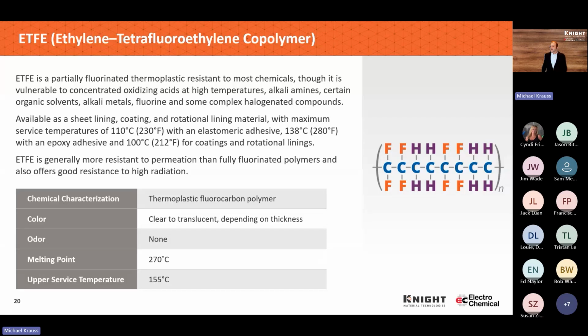There are challenges in getting a thick film spray coating, but this is a material that has been used and does extremely well for rotational linings. So it's not uncommon if you're looking at a rotolining application to end up with ETFE because it works really well. Again, chemical resistance is going to be very similar, and in most cases almost interchangeable with ECTFE. There are several manufacturers of the ETFE resin, but it's also the least available as a sheet lining material. So it's something that can be obtained, but it's usually not a material that someone has on their shelves sitting around. So it's not a major issue, but it's something to be aware of.